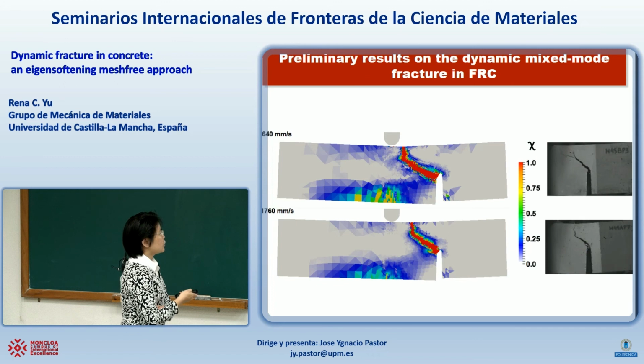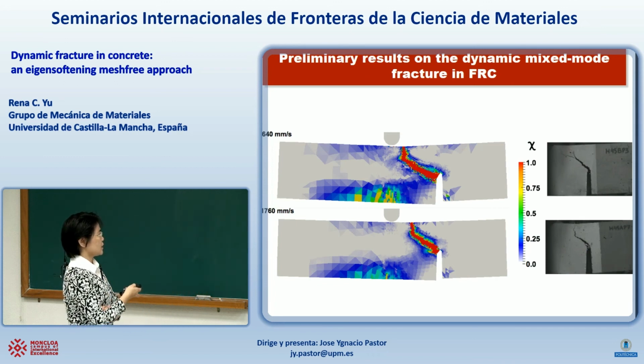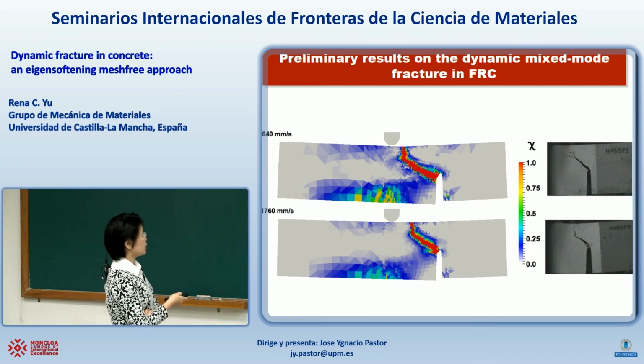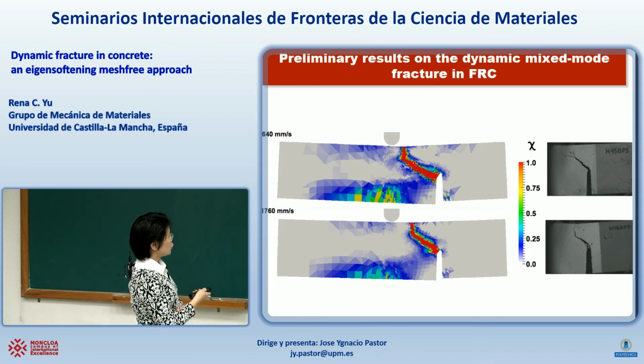Another one, if we try to add fibers, because this is very preliminary work, we see that due to the existence of the fibers, we don't have this main crack at the loading section, but only this crack. They change direction due to the load velocity and also the amount of fibers.